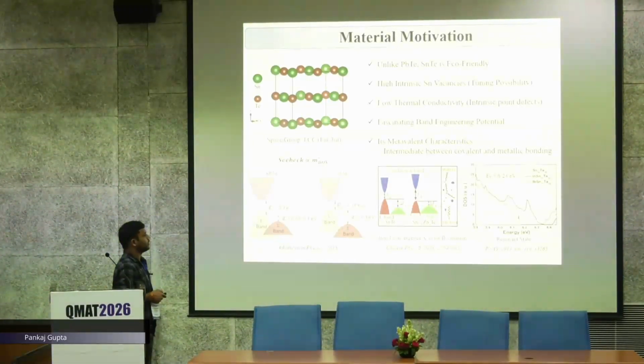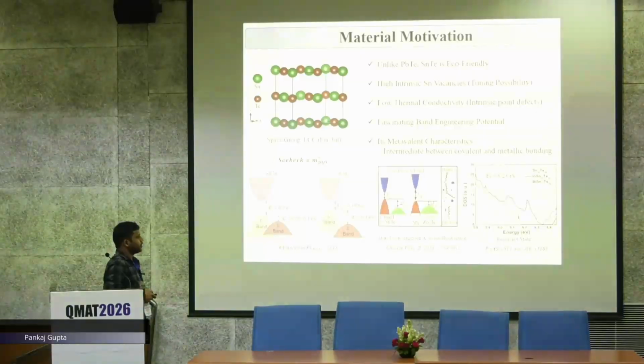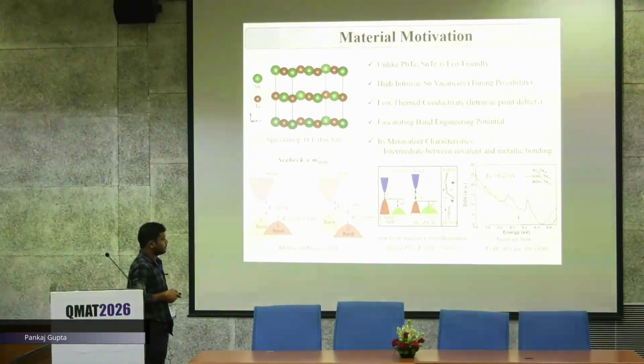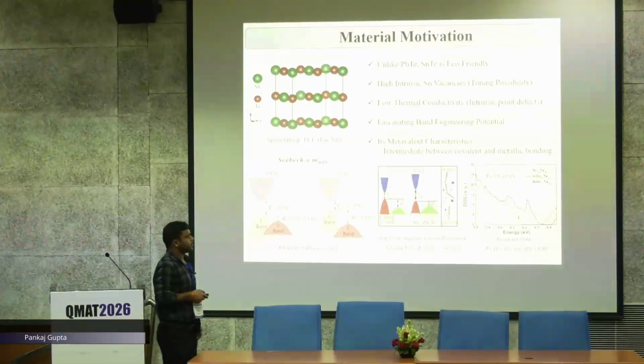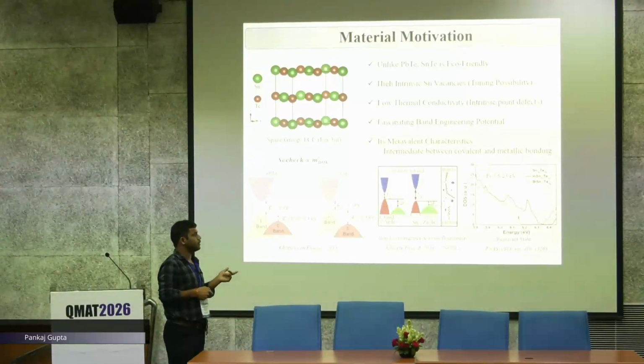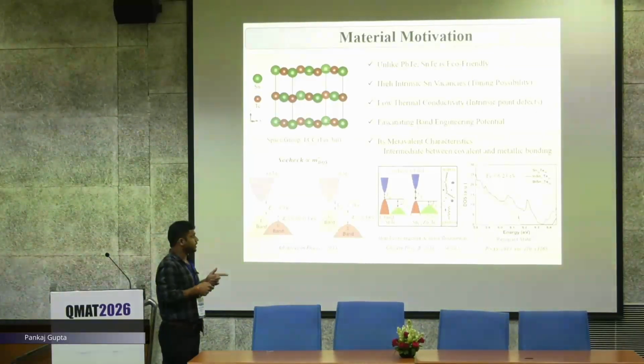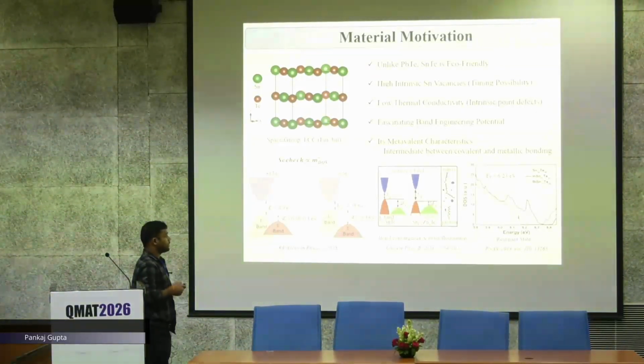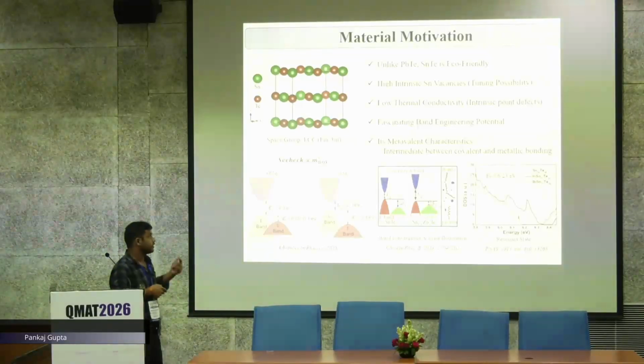Previously people have reported that zinc doping is going to bring some band convergence, reducing this band offset. And also people have reported that indium doping in SnTe is going to bring some resonant state, that means a high density of states near the Fermi energy. And this too helps increase the density of states effective mass, hence a higher Seebeck effect.